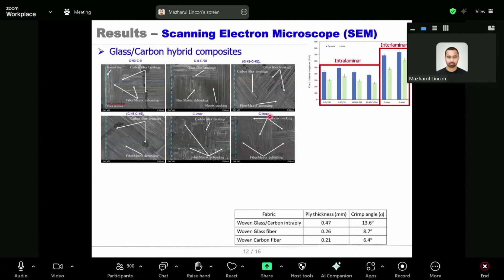Both hybrid composites consist of glass and carbon fiber. However, there is a considerable fracture toughness difference between these two composite types. The intralaminar hybrid composite shows higher thickness compared to the interlaminar hybrid composites. Thickness is almost doubled, and this thickness actually creates a high crimp angle.